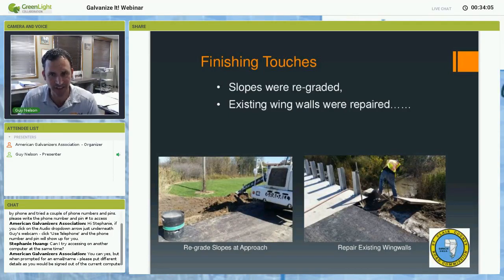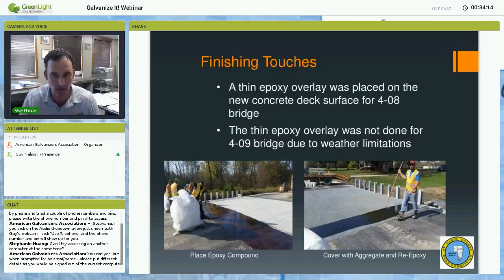And then again, finishing touches, seed and sod, the regrading of the slopes, some repair work on the existing wing walls, seeding and sodding. The county wanted to come in and apply a thin epoxy overlay on both of these bridges. And they were able to do that on 408, which was the bridge that was done first. So on 408, they came out before opening to traffic and applied a thin epoxy overlay for a protective wearing surface on top of those